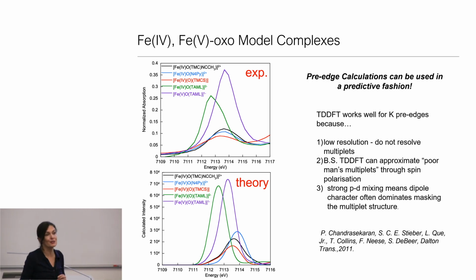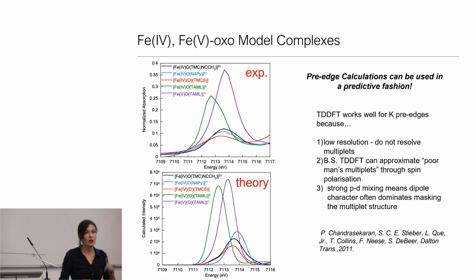And one of the reasons it works so well, especially in high-energy core X-ray spectroscopy, I think, is because our resolution is so poor. You can look at these pre-edges, they're relatively featureless. We actually have an intrinsic core hole lifetime broadening that is larger than an electron volt. And so in effect, our data and the core hole lifetime broadening is masking probably a lot of those multiplet effects. There are some multiplet effects, though, that TD-DFT can capture. And this is really through spin polarization that we can kind of get what we refer to as poor man's multiplets. And I'll show you a bit what that looks like, how spin polarization manifests in these calculations. But the other aspect is that p-d mixing means that dipole character can actually mask the multiplet structure. And so if you think about the fact that, for instance, in this oxo, I have strong pz dz squared mixing.